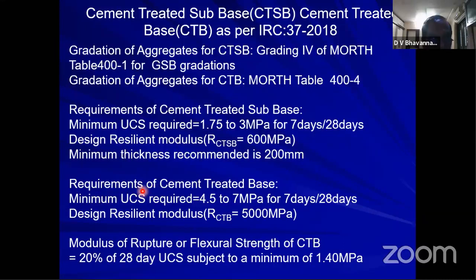Similarly, for CTB, minimum UCS required is 4.5 MPa at 7 days and 7 MPa at 28 days. Design resilient modulus of CTB is equal to 5000 MPa. We have to design how much cement we have to use for CTSB, and the minimum cement requirement is 2%. For the cement treated base, you have to use more cement. We shall get these UCS values and resilient modulus values, so we have to design in such a way.